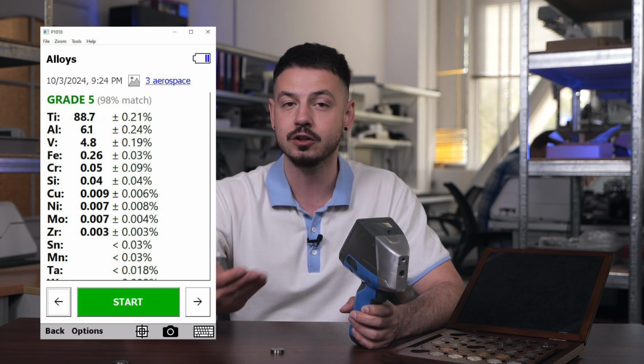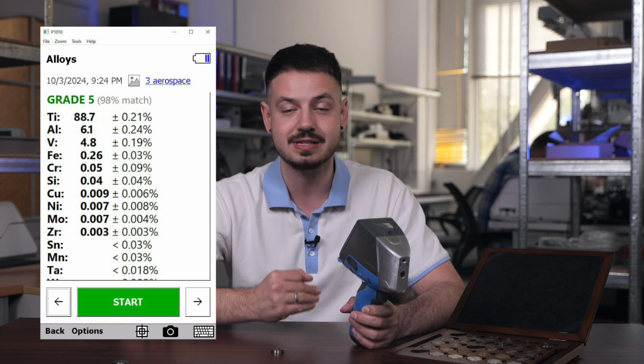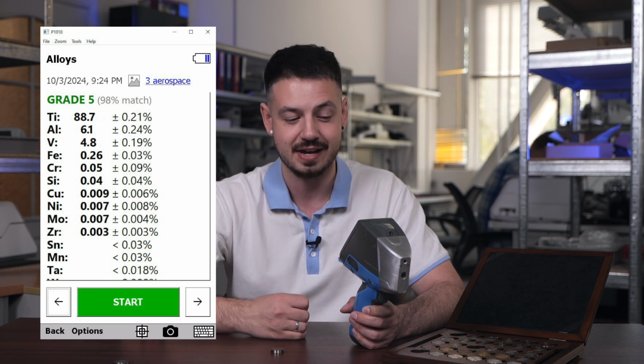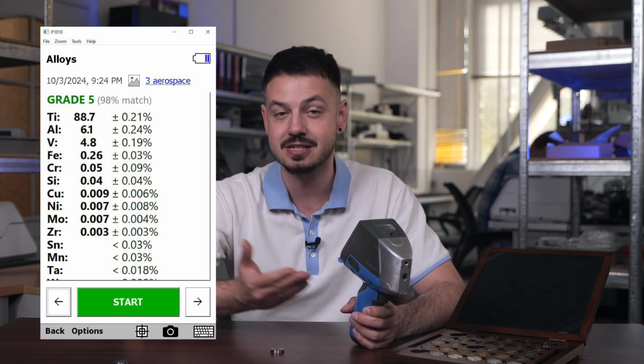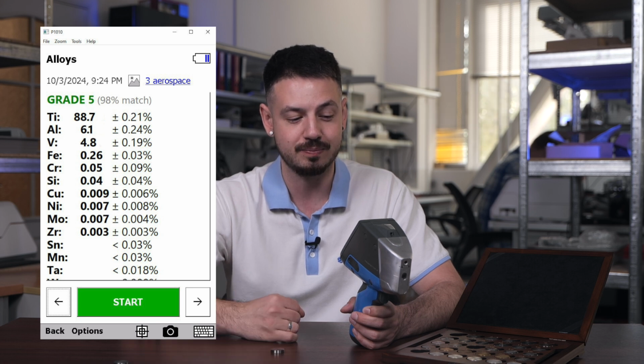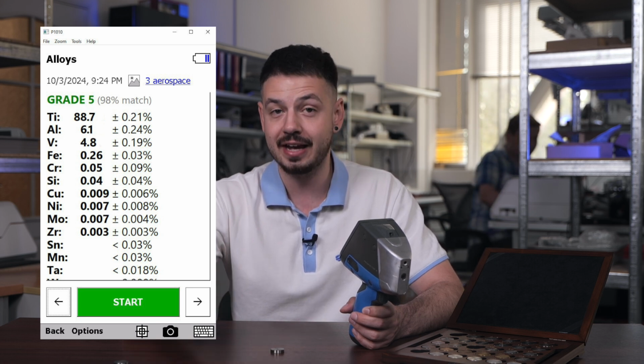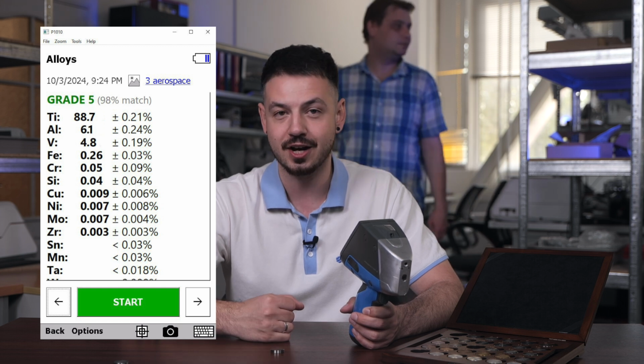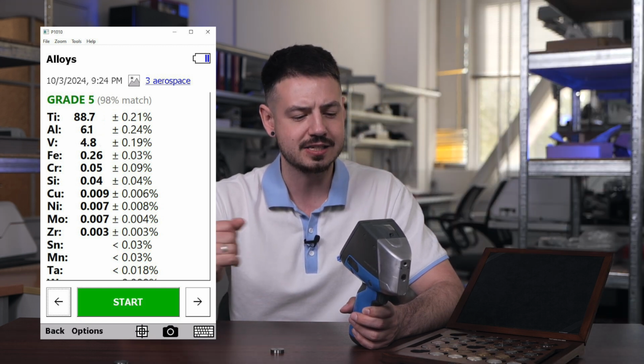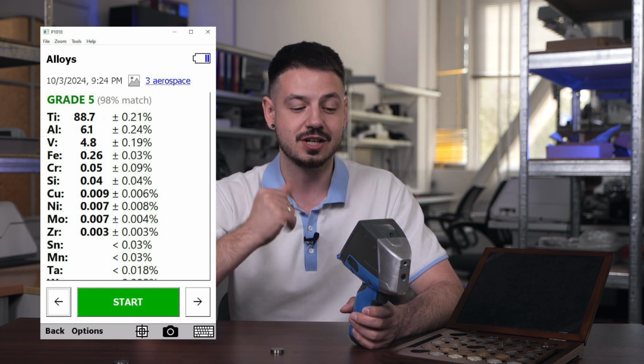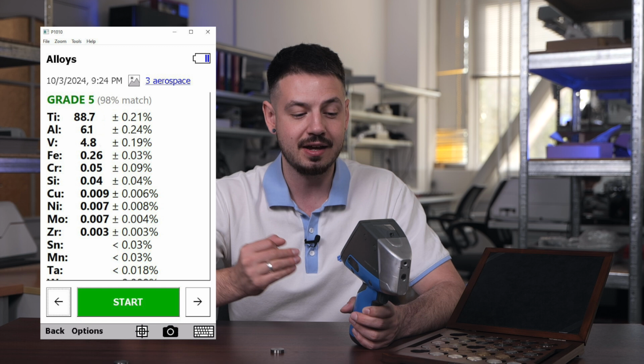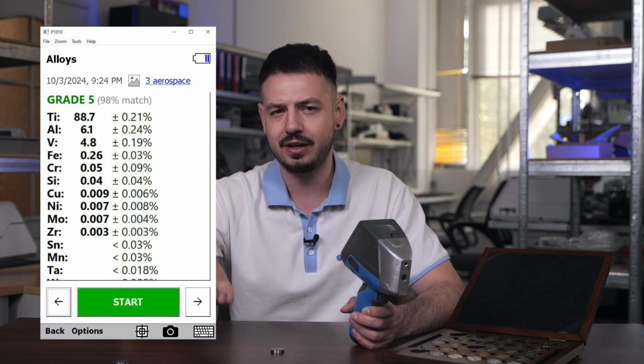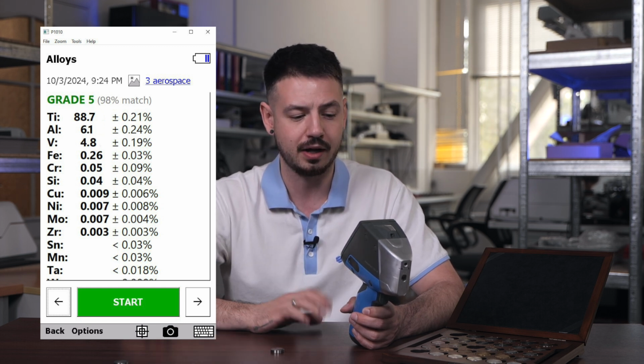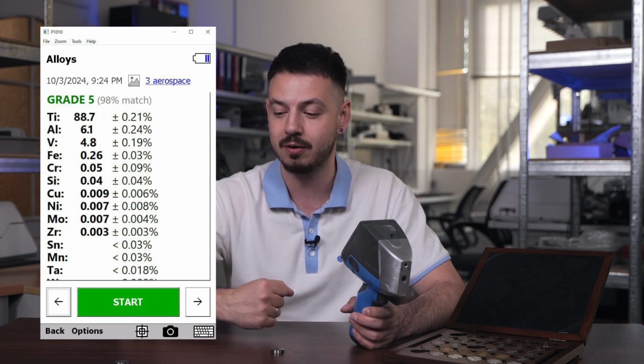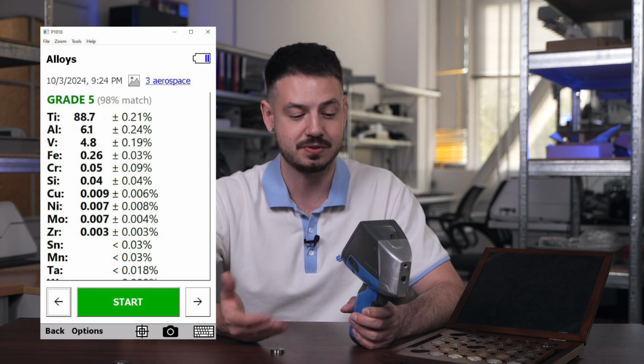Next we have aluminum in a concentration of 6.1, just a little bit over 6, and the appropriate data for this element is 6. So we also fit in here. And also we have vanadium here with a concentration of 4.8 with an acceptable error of 0.3%, and the appropriate data for this element is 4%. So here we fit absolutely well, again, as with our previous two samples.